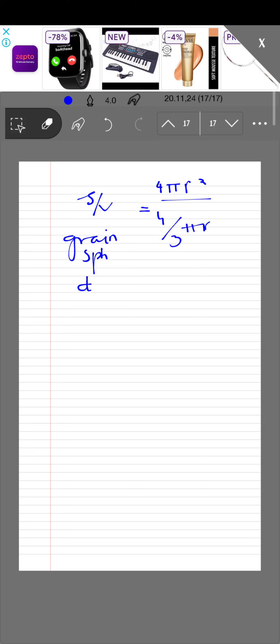Now, in the case of nanomaterials, the factor that comes into the picture is the surface to volume ratio. If we assume the grains to be of spherical shape, that's why we present them as D, considering it is the diameter of the grains. So surface to volume ratio, especially for the case of the sphere: surface is 4 pi r square and volume is 4/3 pi r cube. So it's effectively proportional to 1 by r. So a decrease in the radius or the diameter will cause an increase in surface to volume ratio. The smaller the crystallite, the more will be the surface to volume ratio.